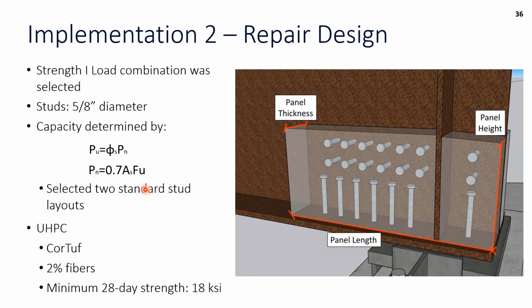And the UHPC we used here, CorTuf, was ultimately selected by the contractor with 2% fibers, and we had the same 28-day compressive strength noted in the specification as 18 KSI.